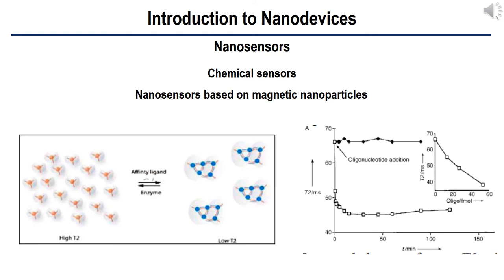Superparamagnetic nanoparticles self-assemble in the presence of a target with a corresponding decrease in solution T2 relaxation time. Self-assembled nanoparticles can be dispersed by the action of an enzyme, temperature, or pH change depending on the nature of the bond holding the nano-assembly together. Magnetic nanoparticles form clusters upon addition of a complementary oligonucleotide, resulting in a quick and significant decrease in spin-spin relaxation times T2 of neighboring water molecules at 40 degrees Celsius. When a non-complementary oligonucleotide was used, no change in T2 was observed. At 1.5 Tesla, significant differences were readily apparent by MRI between samples in the low femtomole range.